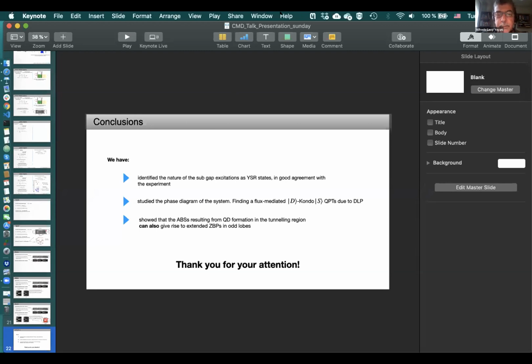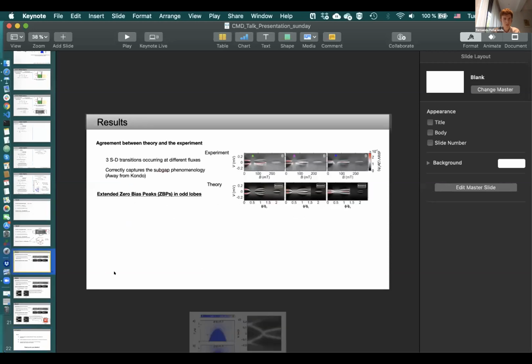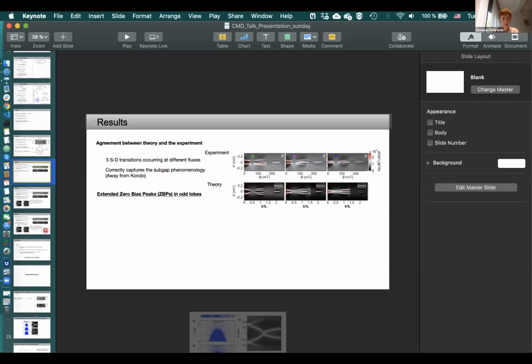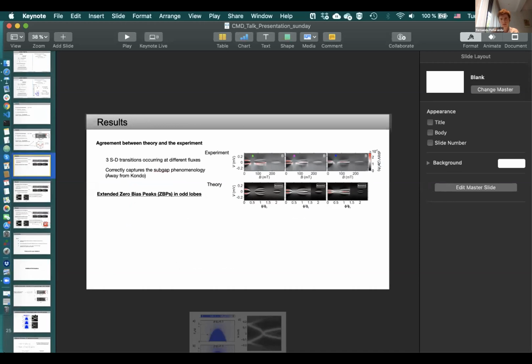Can you tell us what the fitting parameters are when you compare with the experiment? Okay, do you refer to these graphs? Yeah, these ones. Exactly. Well, gamma S is the coupling to the superconductor, as well as gamma N, which introduces finite broadening, fitting parameters, but also the radius and thickness of the wires have to be determined by the Little-Parks formula. The rest are well-known parameters extracted from the experiment, the charging energy.